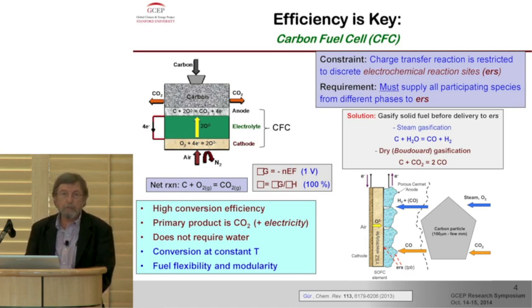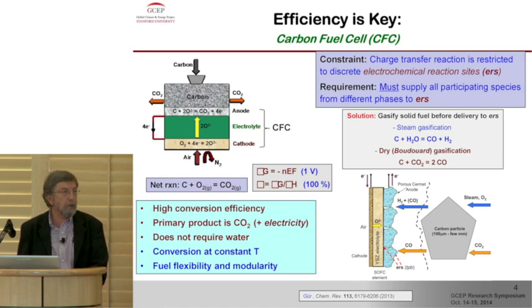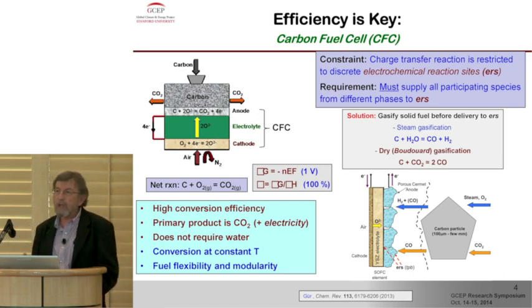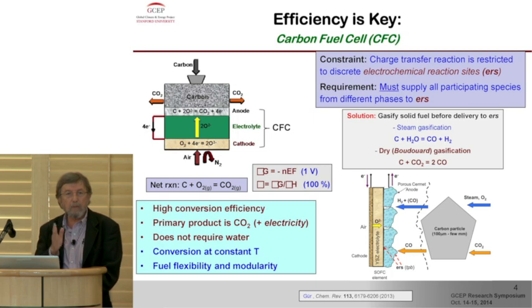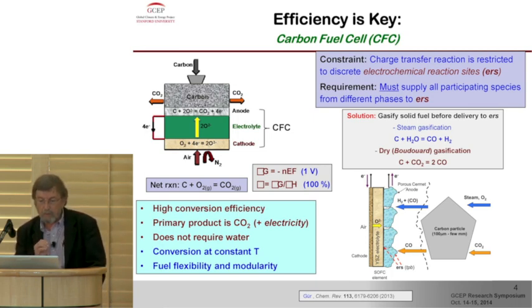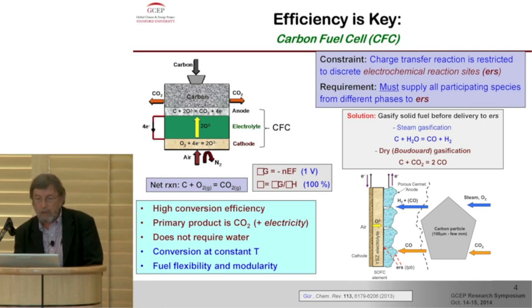One of the major constraints is that we all know electrochemical reactions or charge transfer reactions occur on discrete sites at the interface. And that interface is usually between the electrode and the electrolyte. And these are atomistic or atomic scale sites where these reactions will occur, because the site has to collect all the participating species that reside in different phases at that interface. And that's where the problem is, because you have a boulder of a carbon particle which has sizes anywhere from, say, 50 microns to millimeters, and it has to make atomic scale contact at an electrode site to make this electrochemical reaction happen.